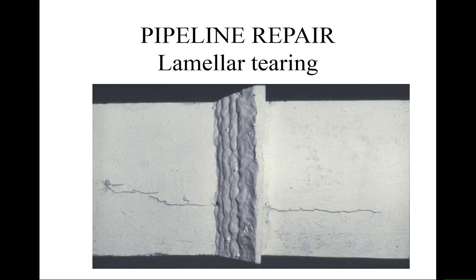So actually what we have in this particular case is a weld. You can see it looks fairly random and very strange. This is the end of a sheet. So you've got your pieces that you put together, you've welded along the length of it, and then this is then welding down the ends to make sure that it's all finished up, and it's just created the lamellar tearing within the shell that's being applied in this particular case there. So you sometimes can see it by eye at the end of the welding process, and then you think, why did I do this? Because I've now got a repair that I've got to make.